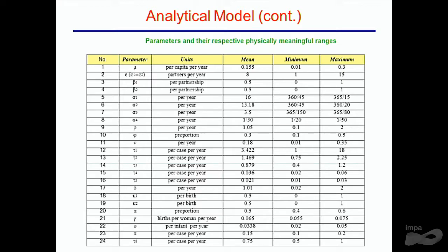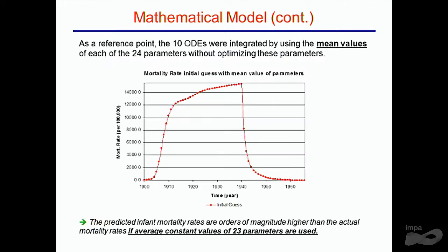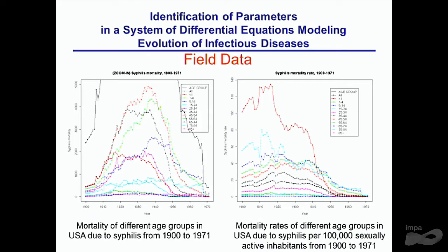So Lloyd said, oh, what the heck? Let's just try the average value between minimum and maximum for each of these 24 coefficients, and let's run this system of 10 ordinary differential equations with these average values of the unknown coefficients. Here's the result. We predicted that there will be 14,000 deaths per year maximum, while the number actually is 120. We got an error of 2 orders of magnitude by using just the average values of these coefficients. So obviously it is total nonsense. Okay? Don't use average values. How about it?